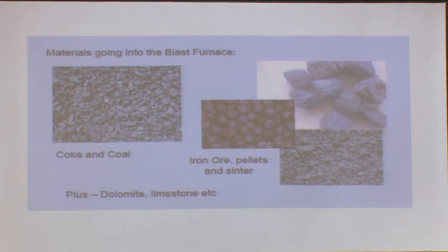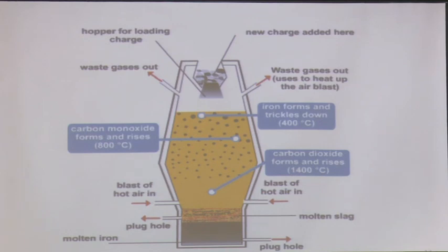The raw materials going into the blast furnace are coke and coal. Some portion of coal is charged through the tuyere region where oxygen is injected — this is called pulverized coal injection, or PCI. That is around 10 percent non-coking coal, charged through this route to reduce coke consumption. This is a development from the last 20 to 25 years. Along with the blast of hot air, fine coal dust is injected to raise the temperature.